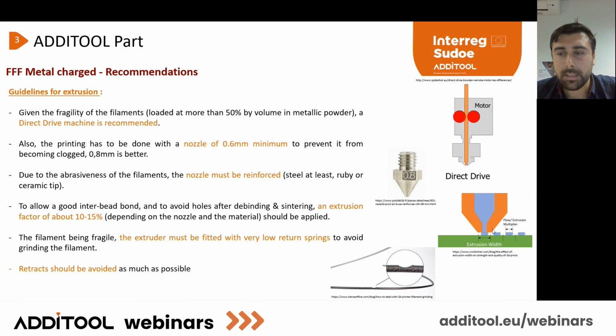Also, with this kind of filament, and it's different from pure polymers, we want to avoid every space on the interbead bond, to avoid holes. After debinding and sintering, we have to over extrude. We have to put an extra extrusion of about 10% or 15%. It depends on the nozzle and the material you're using, but you have to over extrude a little bit.